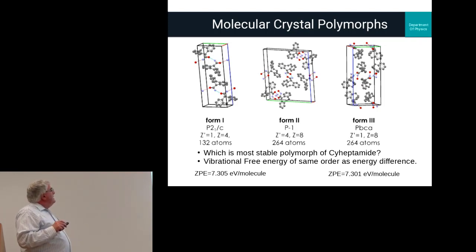The relative energies, of course because the molecules are intact, are very similar. The molecular energy doesn't change. A lot of this is in the bonding energy. We've been doing calculations with CASTEP using various dispersion-corrected PBE functionals. But it's clear that the energy difference is insufficient to establish stability. What we need is the free energy difference.